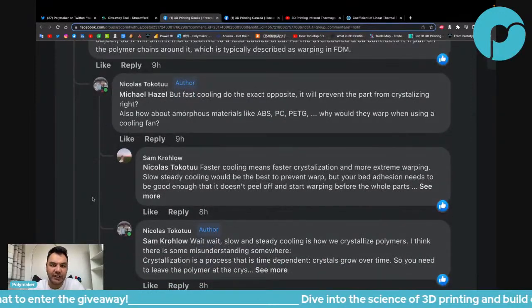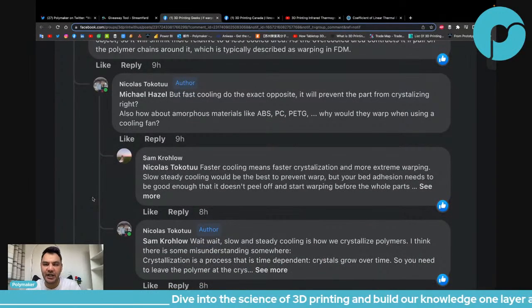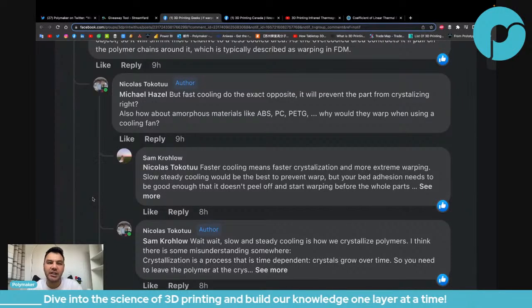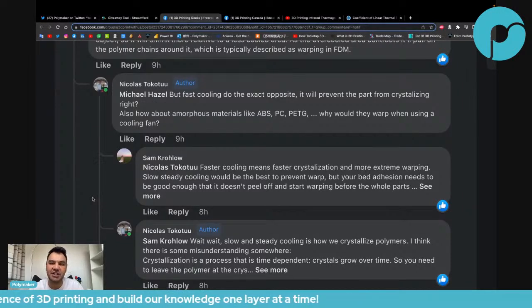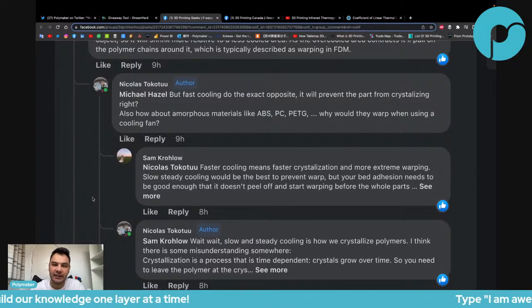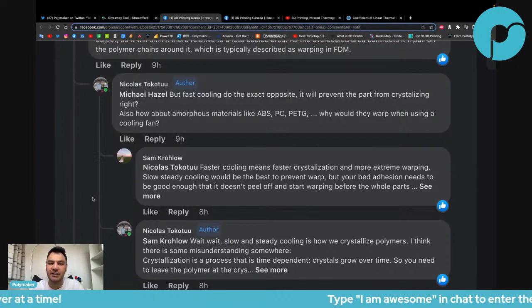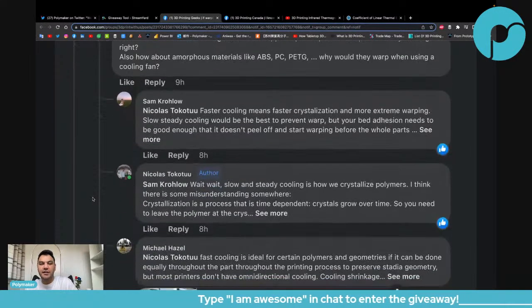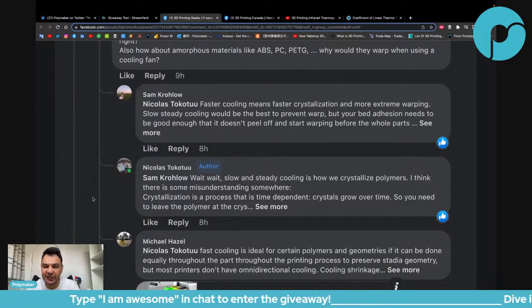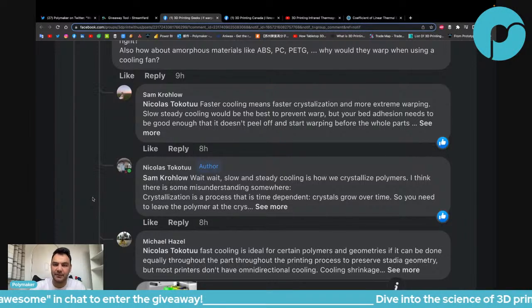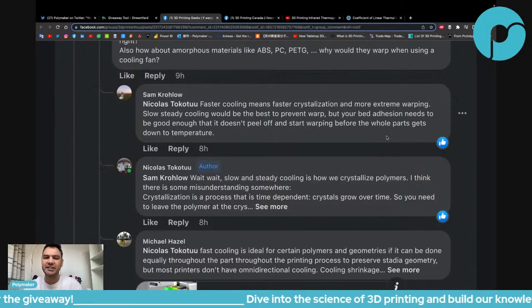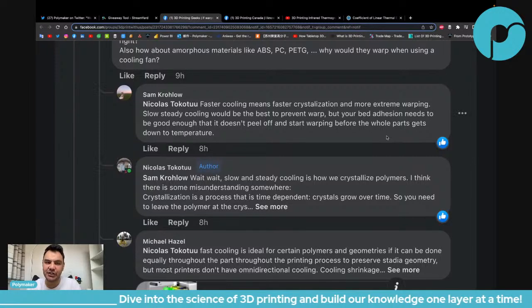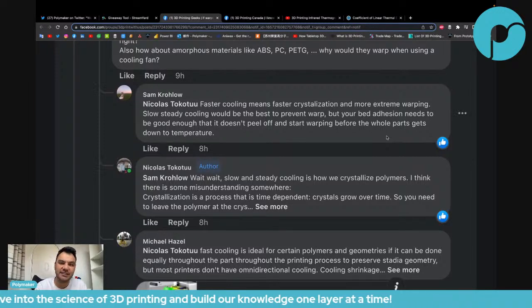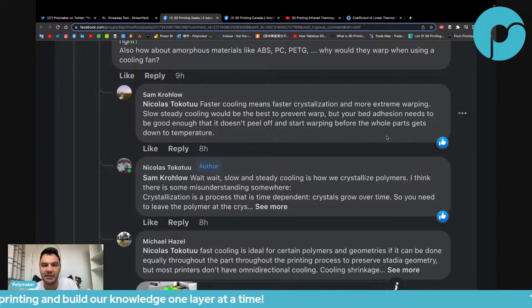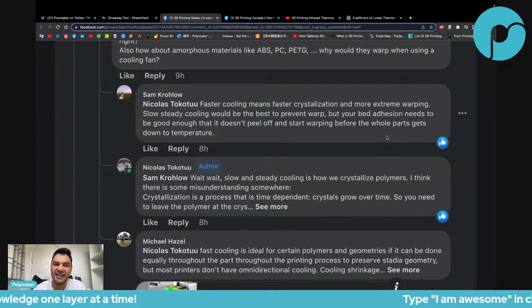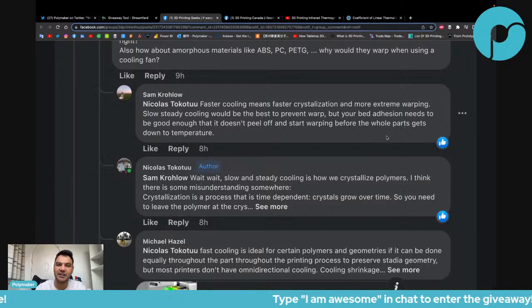Okay, so my answer. But fast cooling does the exact opposite. It will prevent the part from crystallizing. Also, how about amorphous material like ABS, PC, and PETG? Why would they warp when using a cooling fan? Because they don't crystallize, right? The amorphous material. Faster cooling means faster crystallization and more extreme warping. So you can see that there's already something strange. I mean, faster cooling is the exact opposite, it prevents crystallizing. But anyway, you're going to realize that what he means by crystallization is completely different, actually.